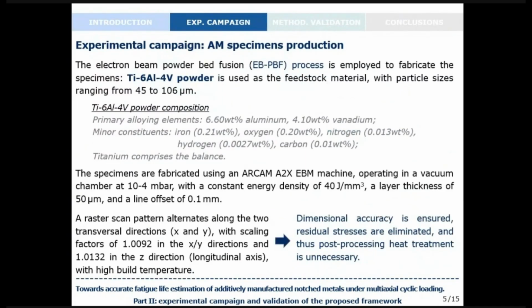So let me now describe to you the experimental campaign carried out on additively manufactured specimens. In particular, we employed the electron beam powder bed fusion process to fabricate the specimens, and a titanium 6 aluminum 4 vanadium powder is used as feedstock material with particle sizes ranging from 45 to 106 microns. The details on the powder composition are shown here, as well as the main process parameters.